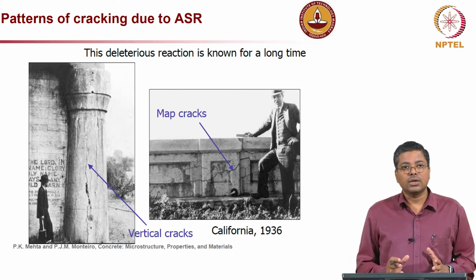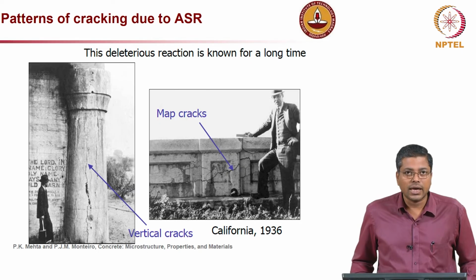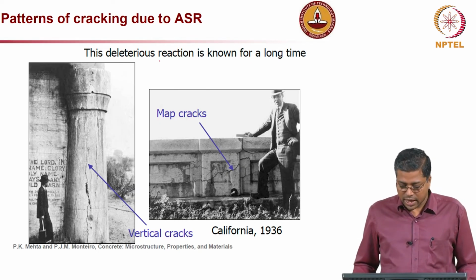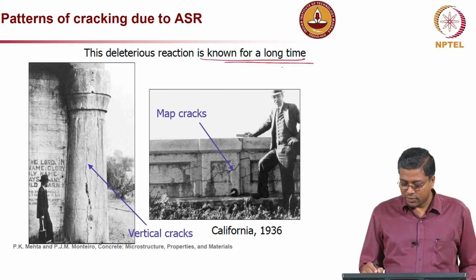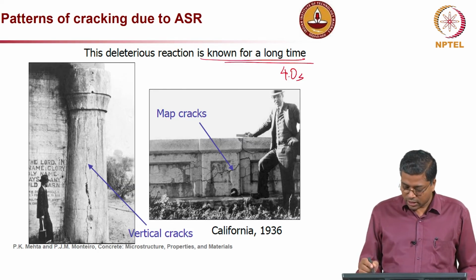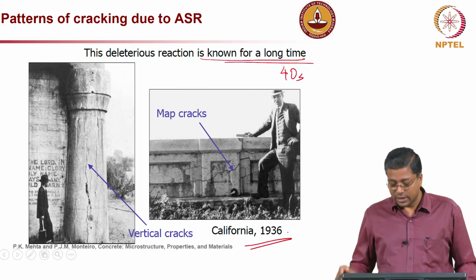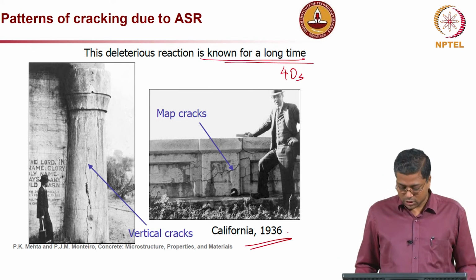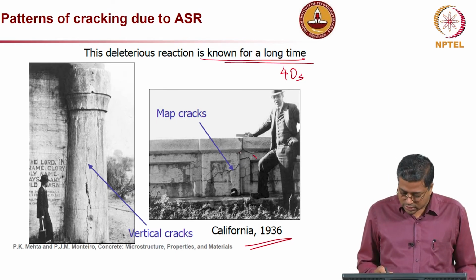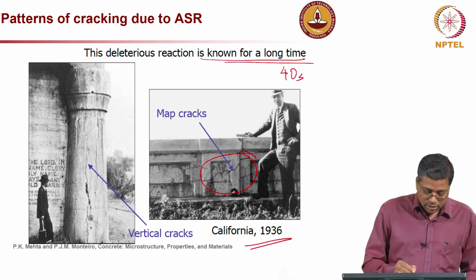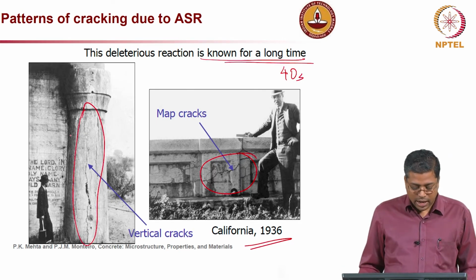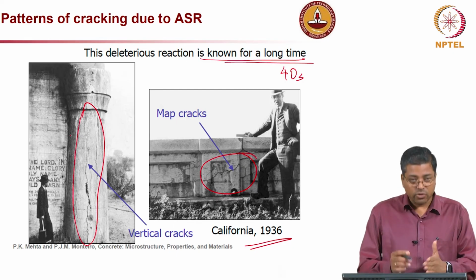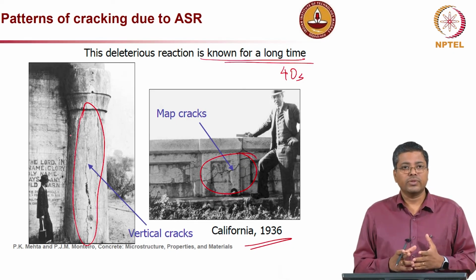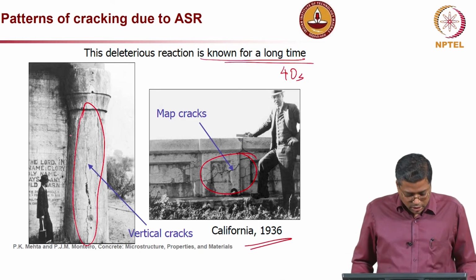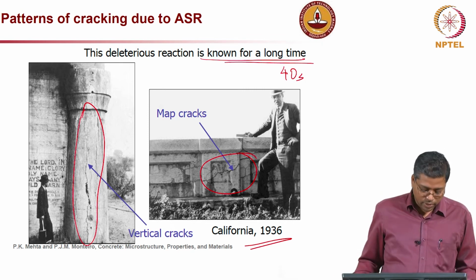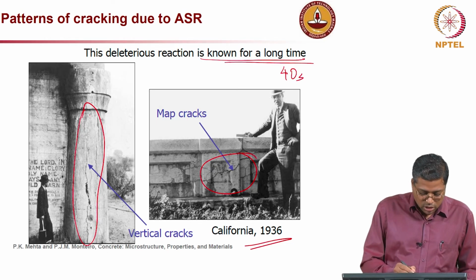Now, how does all this gel formation lead to the type of cracking which we observe, and how can we detect it? This deleterious reaction is known for a long time. In the 1940s itself, people identified this and published it. In this picture, you can see 1936, which is one of the first images showing ASR induced cracks. You can see it is map cracking, not in a specific direction, and here you can also see vertical cracks on a column, because on the column you have reinforcement, and when there is a reduction in the strength of the concrete, the reinforcement will try to push the concrete. In other words, the crack is along the stress path, but it is not a straight line crack.